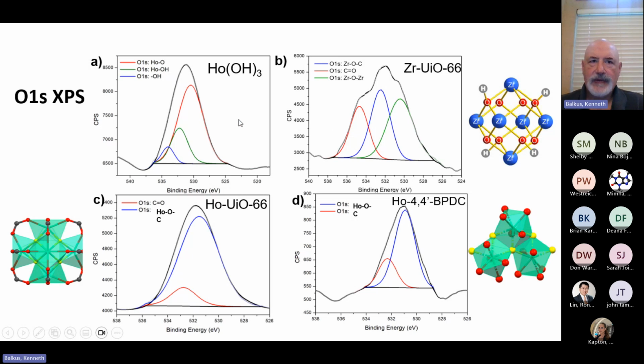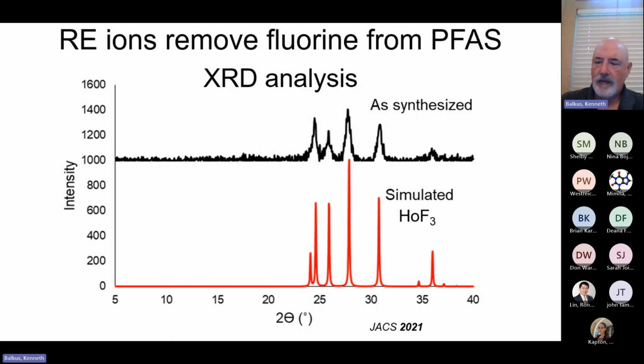So then if you go over to the metal organic framework, there is no binding energy, there's no peak for an oxygen bridge, okay? And this is just a trinuclear cluster with a different linker, and same thing. We don't see any evidence for oxygen bridges. So early on, the first structures we made, there was only fluorine in the framework.